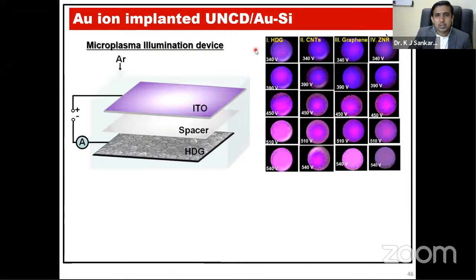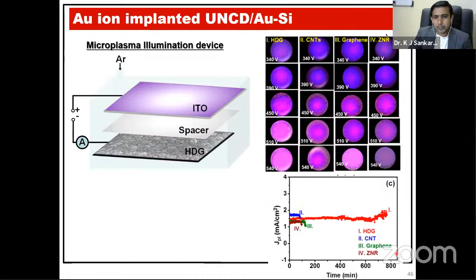We also used this gold-implanted UNCD on gold-coated silicon for microplasma devices, and the hybrid material with diamond and gold shows a very good intensity plasma even with low applied voltage as compared with the other field emitting materials, and the lifetime stability is also very good as compared with these other field emission materials. And if you would like to know more about these diamond-gold nano hybrids for enhanced cathode material for field electron emitter applications, I would suggest you go through my review article, recently published in 2021 along with my supervisors in Belgium and in Taiwan.